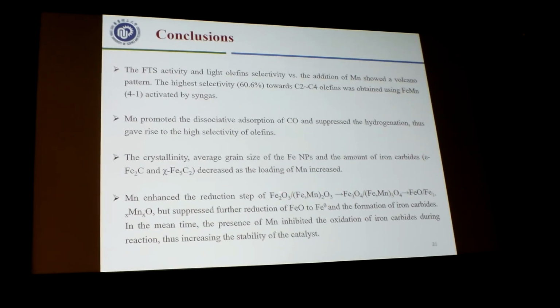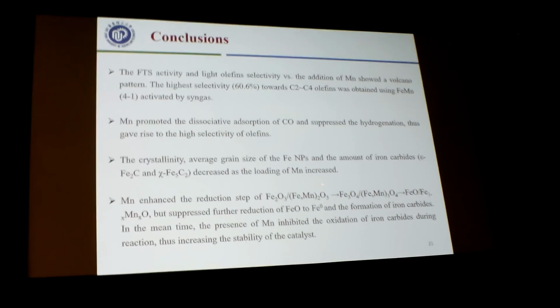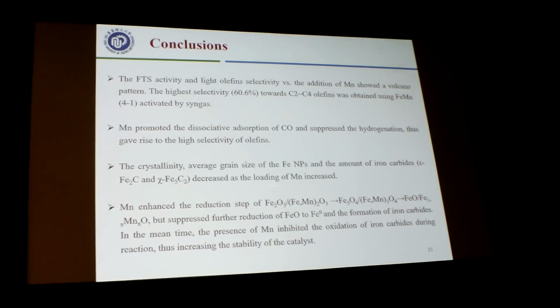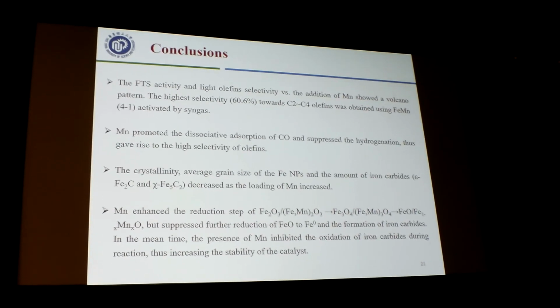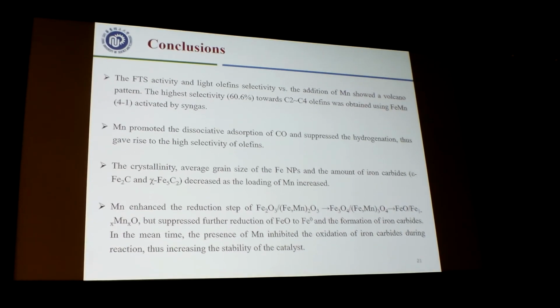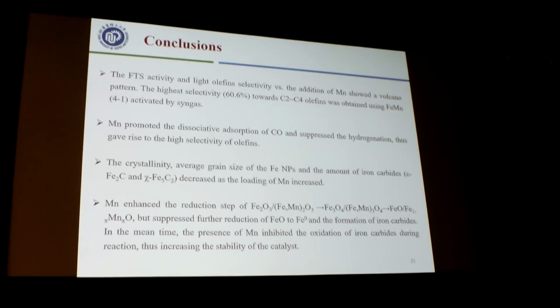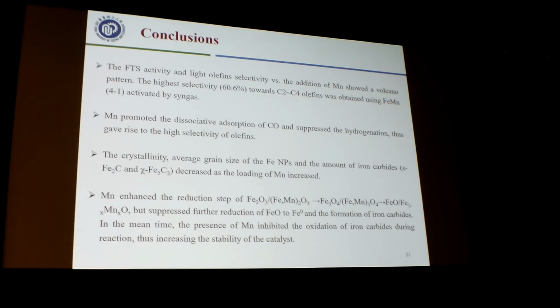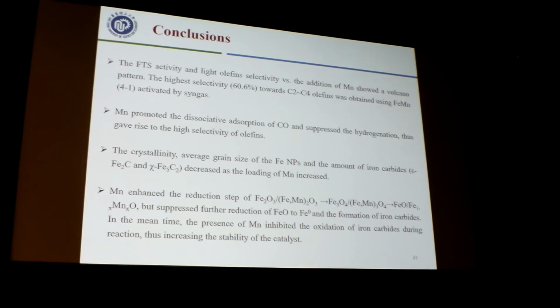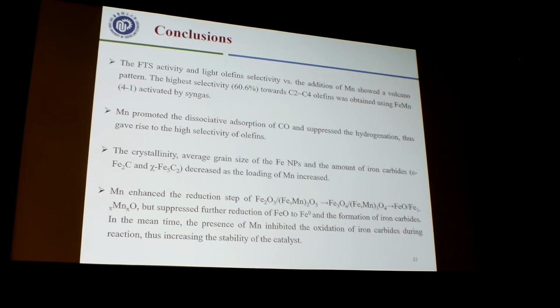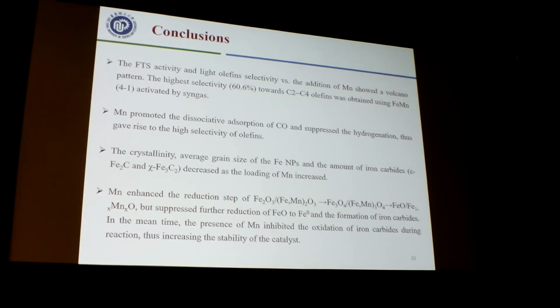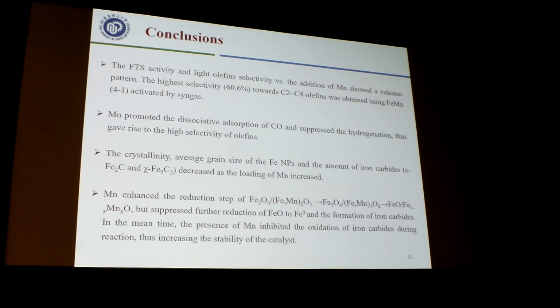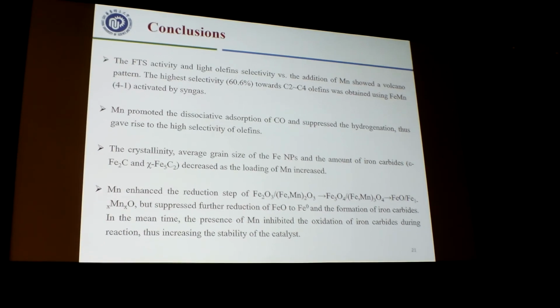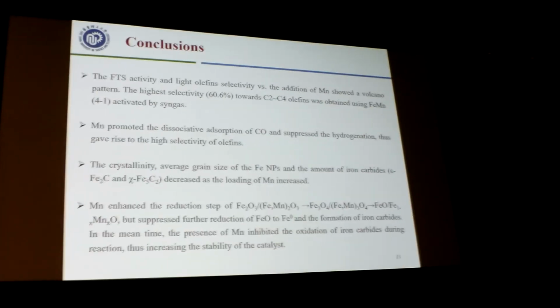And the average grain size of iron nanoparticles and the amount of iron carbide decreased as the loading of manganese increased. And finally, the manganese enhanced the reduction step of iron 3 to magnetite and stabilize the iron 2, but suppress the further reduction of iron 2 to iron 0 and the formation of iron carbide. So that in the meantime, the presence of manganese inhibited the oxidation of iron carbide during the reaction and increasing the stability of the catalyst.